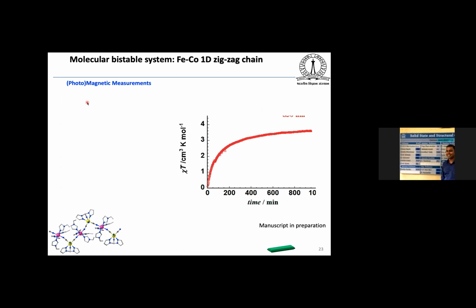So what we have done, we use a thin film of the system and we irradiate it in the SQUID magnetometer using 830 nanometer laser light that is available in the lab, and we first cool down the system to 10 Kelvin. Then we use this 830 nanometer laser light, with a very small power of 3 milliwatt per centimeter square, and in a 1 Tesla magnetic field you can see the system is converting from the diamagnetic to the paramagnetic state.